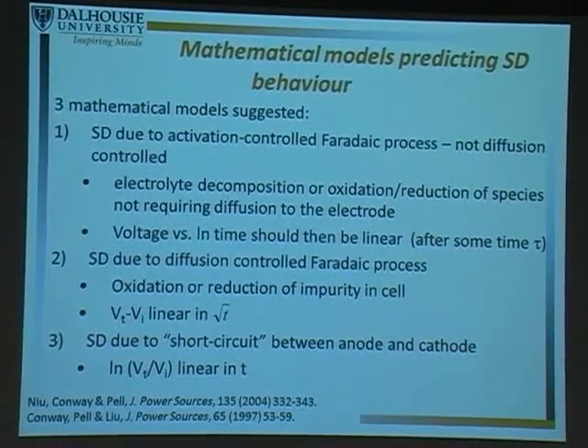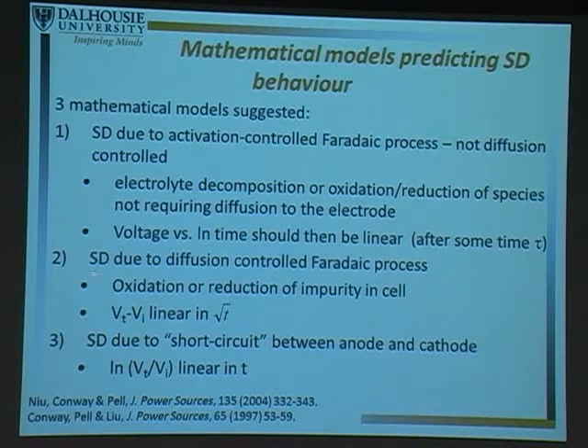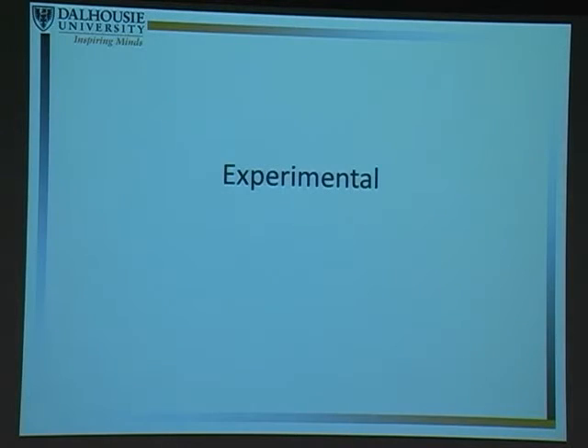And so we plot our self-discharge profiles versus log time and look to see if it appears to be activation-controlled. We also want to look for diffusion-controlled reactions. So this is where you might have a reaction of something that's at low concentration or an impurity in your cell. And what he modeled was that if you plot potential as a function of square root time, if it's a linear drop, it's a diffusion-controlled process. He also modeled the short circuit between the anode and the cathode. We never actually look at this possible model because, as I'm going to show you, we use three electrode setups. We're really looking at one supercapacitor electrode at a time. So we would never have a short circuit between our anode and cathode.